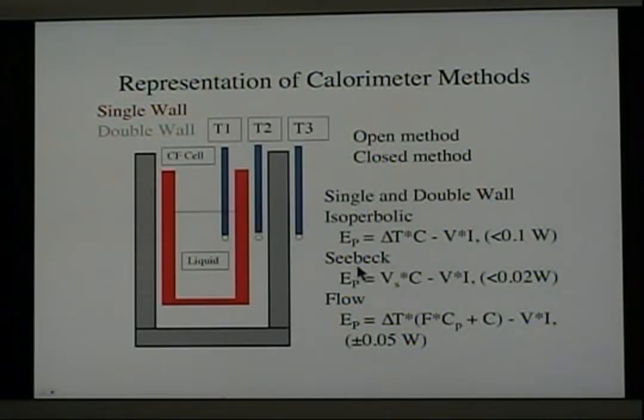In the Seebeck calorimeter, instead of a delta T, one uses the voltage that is proportional to delta T, multiplies that times a constant, and then subtracts the power that's going into the cell. The flow calorimeter calculates the power somewhat differently. The temperature change of the liquid is multiplied by the flow rate and by the heat capacity of the liquid.